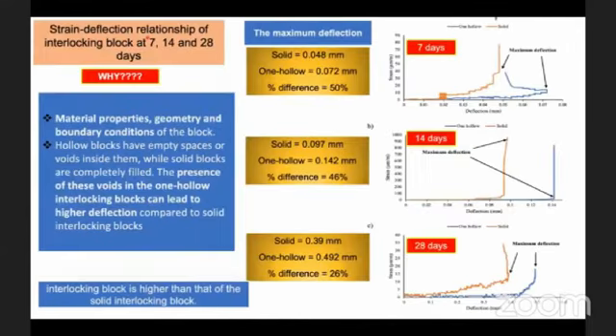So this one is the strain deflection relationship of interlocking block at 7, 14, and 28 days. So this one is the maximum deflection. If you refer to this slide, you can see that the solid block has lesser maximum deflection compared to the hollow one. For example, at 7 days the maximum deflection for solid is 0.048 millimeter, and for the hollow interlocking concrete block is 0.072 millimeter, with a difference of 50%.